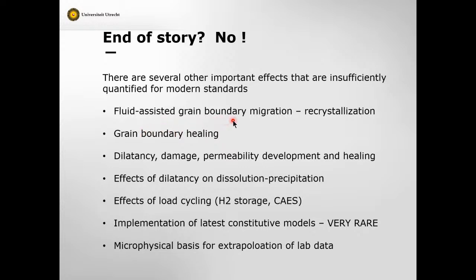There's a process called fluid-assisted grain boundary migration, which I'll show you a few pictures of. These grain boundaries with brine or water in them can heal, and that changes the picture totally. Microcracking, damage going on in the walls of a cavern or cavity, for example, leads to permeability development, but it can also heal. It's not wholly understood in the longer term. How this microcracking interplays with the transport of material around grain boundaries is very poorly understood. We don't know what the effects of load cycling are, and fluids coming in and out of the wall material. How far will it go? What effects will it have?